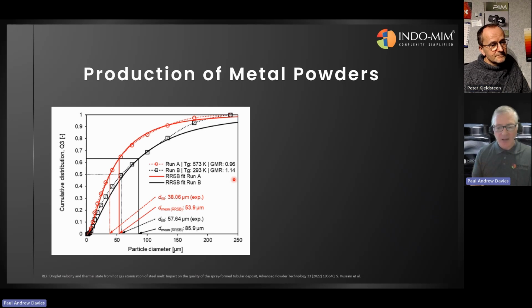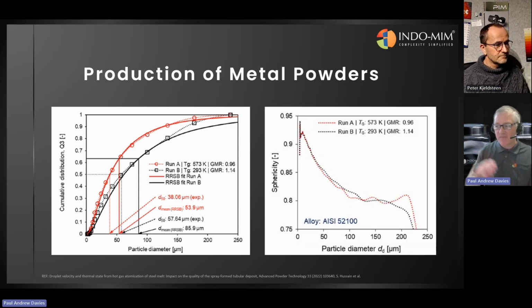So there's probably an optimum, and there are atomizers you can buy off the shelf now, which for laser powder bed fusion tend to heat the gas between 150 and 300 degrees C, for instance, to produce a 30 micron average size, which is bang in the middle of 15 to 53 microns. Fortunately, the shape of the powder doesn't seem to be affected by gas temperature. Here you can see the sphericity versus particle diameter. Often quite a nice trend, though, is the finer you get, the more spherical they become. I guess it's because they freeze quite quickly and the surface tension is higher. But the gas temperature doesn't really affect the shape, it seems.